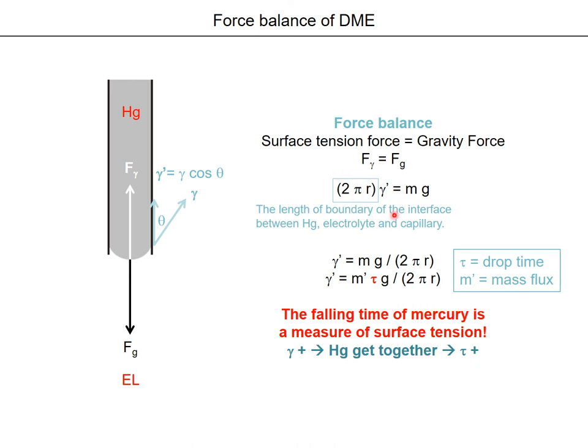So this gamma prime is gamma cosine theta, and the force is calculated by the product of gamma prime and the length of the boundary of the interface between mercury, electrolyte, and capillary. That is to say, the size of the capillary is involved in this equation. So this boundary length is 2 pi r, and here r is the radius of the capillary. So the product of 2 pi r and gamma prime, or gamma cosine theta, is the surface tension force. Then by reshuffling these equations, gamma prime is expressed by mass, gravity, 2 pi, and the radius of the capillary.